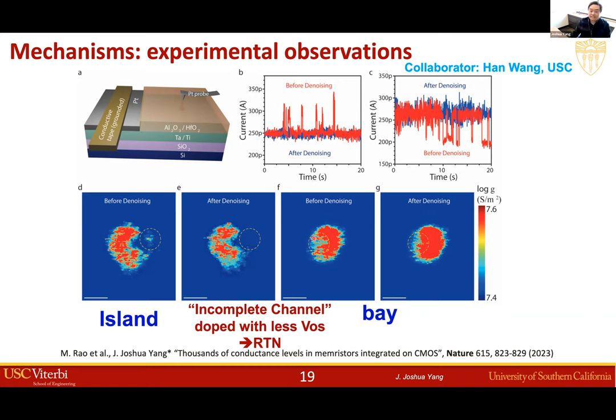So for other devices, before denoising, you can see here is a major conduction channel, but next to it is a region that is relatively more resistive, but it is an incomplete channel. We call this case a bay case. And then we can also denoise it. We can use a voltage polarity that normally would switch the device on. And after applying that small voltage, we can see the noise is gone in the blue curve.